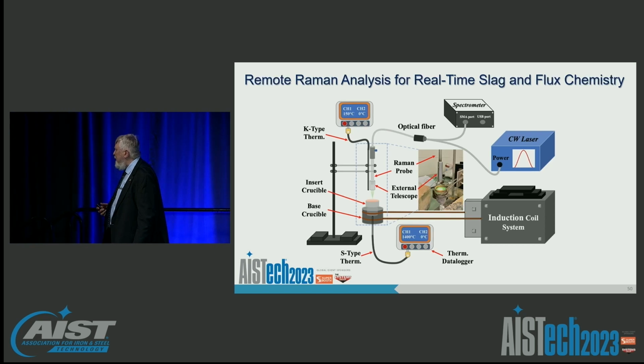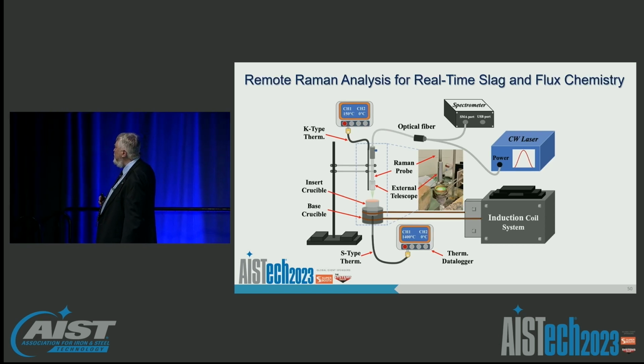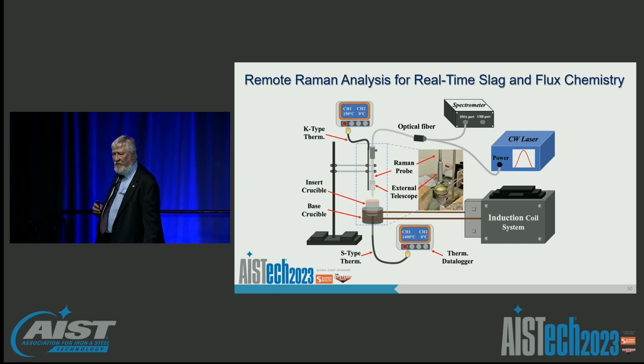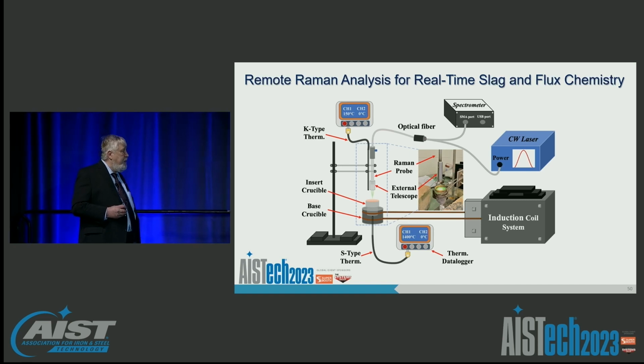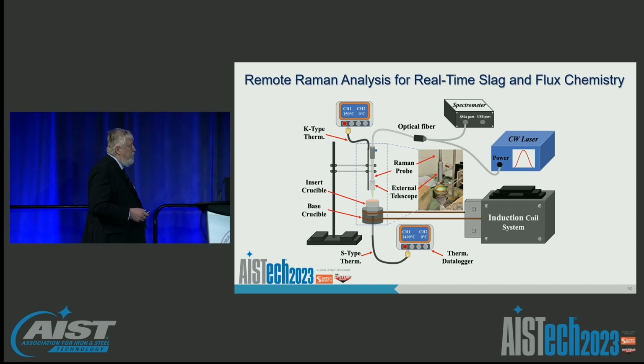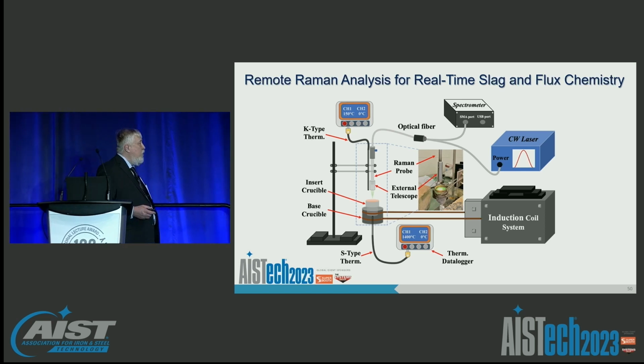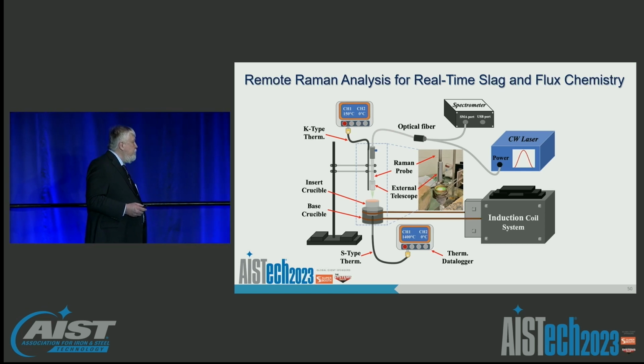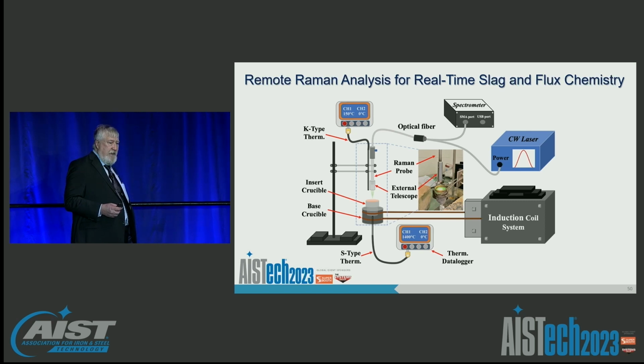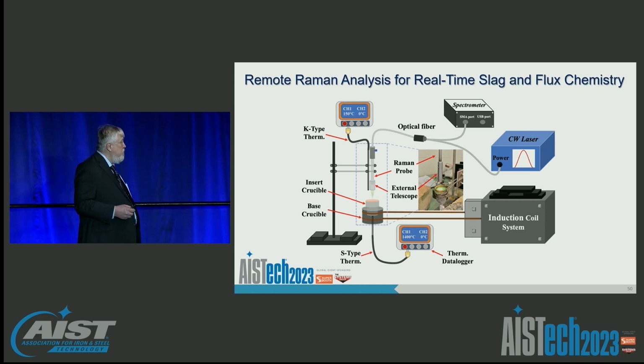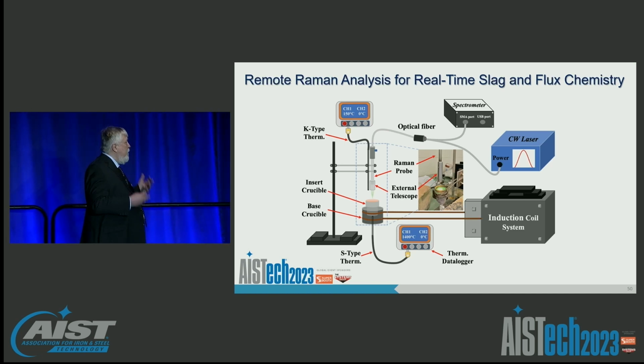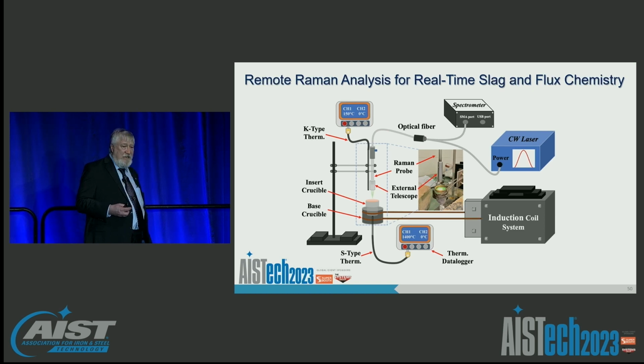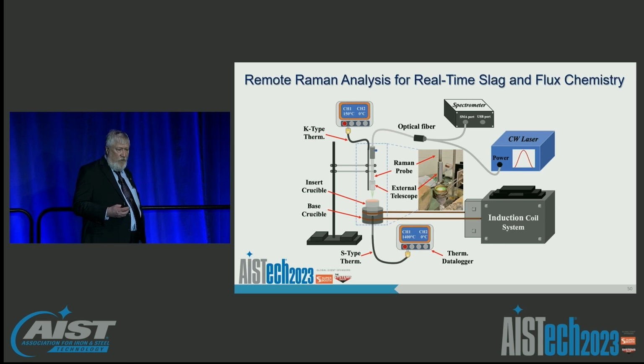So, last area I want to talk about is the potential for using fiber optics as a remote sensor for doing slag and flux chemistry measurement. And here we've built a demonstration system that uses essentially a fiber optic carrier to a Raman probe system that can actually tolerate reasonably high temperatures. And we can actually do real-time measurements of the Raman spectra on fluxes and slags at high temperatures. And in fact, we've demonstrated 1400 to 1500 C so far.